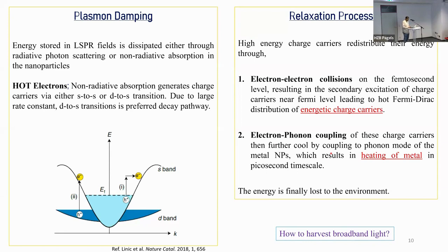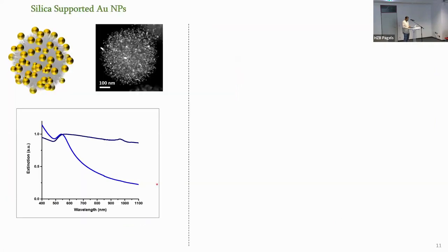Now the question was, how do I harvest the entire broadband of the light? I cannot just harvest 550 or 560. That is not going to make your catalyst really efficient. So the challenge was, if I take say 10 nanometer gold, this is how the light absorption behavior is, around 550 nanometer. And then it drops. What we wanted is something like this, a broadband light absorption, so that every wavelength of the light coming from the sunlight gets harvested.